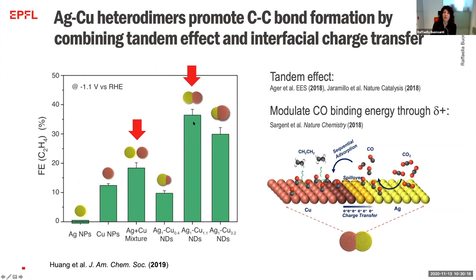So when we have a system like copper and silver, a phenomenon that occurs is referred to as tandem catalysis, because the silver makes CO and then the copper takes care of converting CO into a different product. But here, this is what happens in the physical mixture. Instead, when we create an interface, there is something more going on. And in this case, it is again a charge transfer from the copper to the silver, which can modulate the CO binding energy through this partial charge, similarly to an example that was reported in the literature.